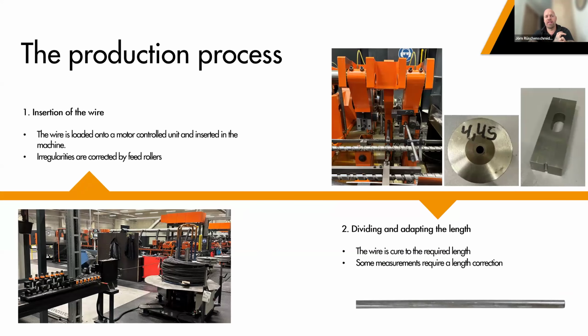So first the wire is loaded onto a motor, so it's driven actively in the machine. It gets straightened and stretched, and then we divide it into lengths. So the screw blank is always a shorter and thinner wire than the final screw. Seeing this die size of 4.45, this will be a 6 mm screw. So the core is 4.45, but it gets rolled out to the width of 6 mm, talking about the nominal diameter of the thread. So our wire always matches the core diameter, which for example here is 4.45 for 6 and 5.75 for an 8 mm screw.